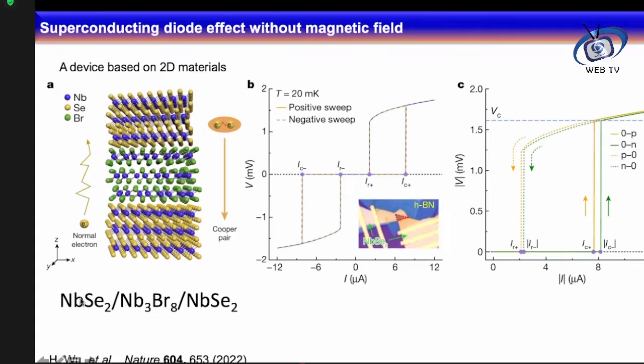But this niobium diselenide, it is a superconductor. So this is a Josephson junction. And in this Josephson junction, they actually observed their IV curves. So the main supercurrent is here, which is the positive supercurrent, and here this is the negative supercurrent.